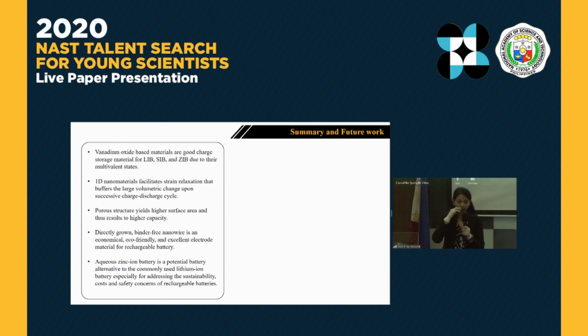1D nanomaterial facilitates strain relaxation that buffers the large volumetric change upon successive charge-discharge cycles, and porous structure yields higher surface area and thus results in higher capacity. So the direct-grown binder-free nanowires is an economical, eco-friendly, and excellent electrode material for rechargeable battery. And most importantly, aqueous zinc-ion battery is a potential battery alternative to the commonly used lithium-ion battery, especially for addressing the sustainability, cost, and the safety concerns of rechargeable batteries.